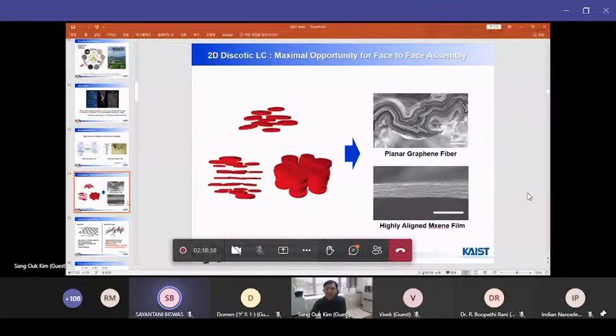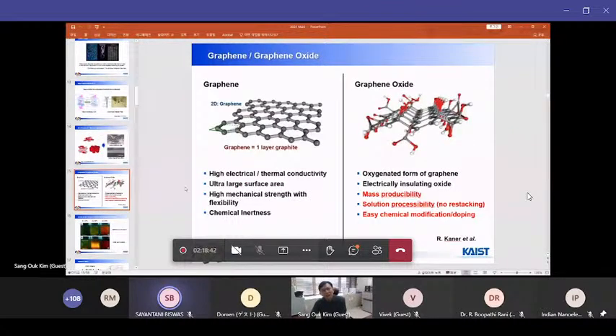For 2D liquid crystalline assembly, graphene can be chemically modified. Originally, graphene has many interesting properties, but it has very poor processability and low dispersibility in common solvents. But after oxidation, you have graphene oxide, as shown on the right side. This graphene oxide can be mass-produced, and it also has high solution processability.